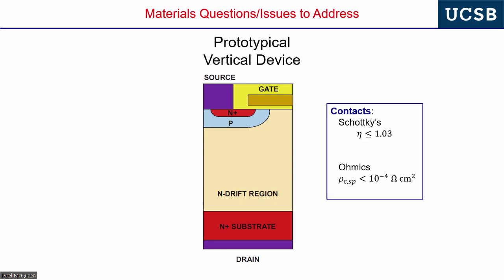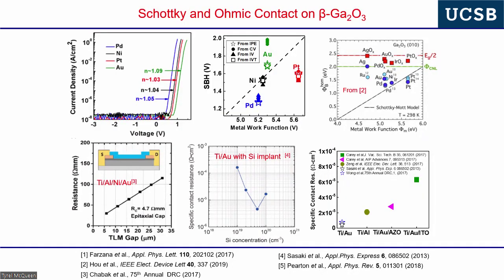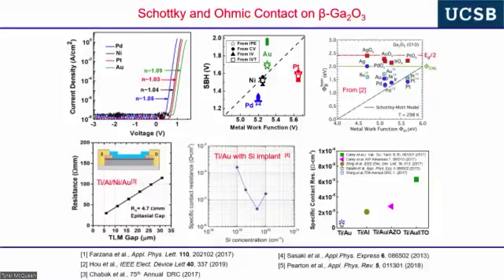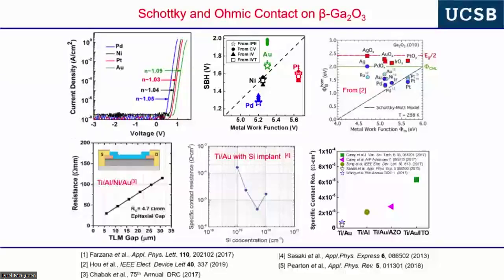So then I'll show you ohmic contacts. And this is work, a lot of it from Steve Ringel's group, who's part of a MURI that I lead at UCSB, okay, showing a wide range of metals, okay? And these papers came out very early in the field. And many of the folks working in this field came from gallium nitride, and gallium nitride on foreign substrates. You would never see JVs for Schottky diodes that look like this. You might see a little region in the log current density dependence on diode bias where it's linear, and then you would see leakage, okay?